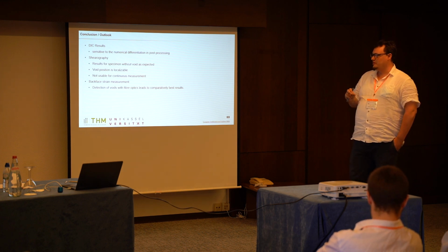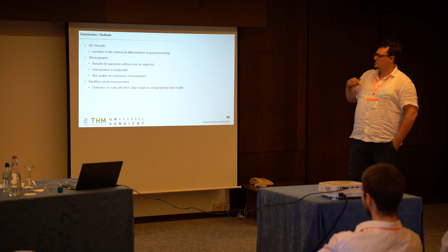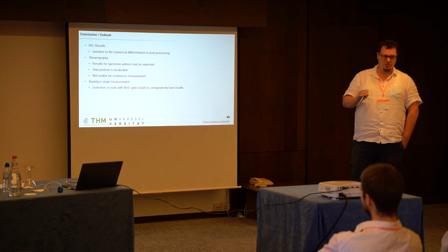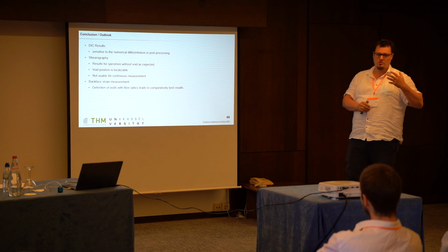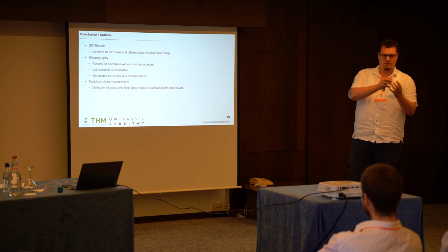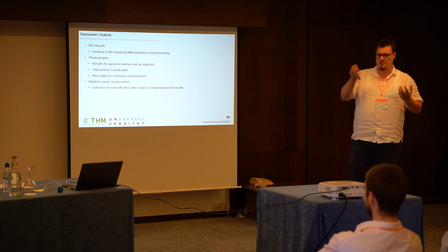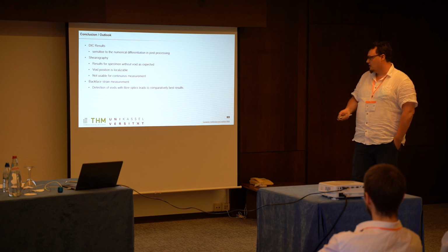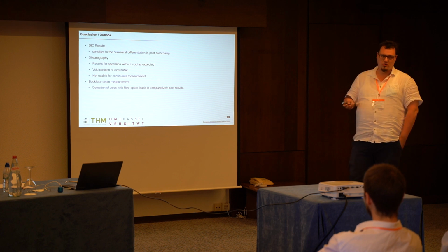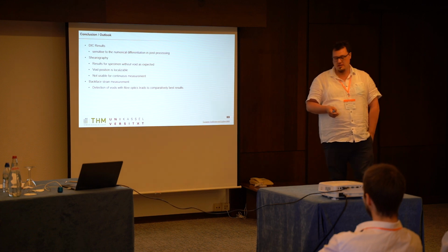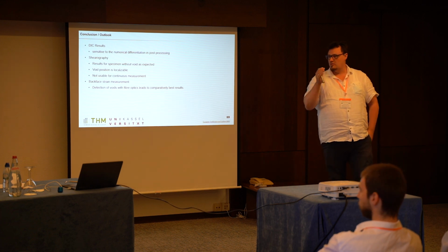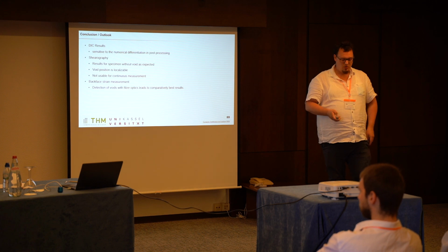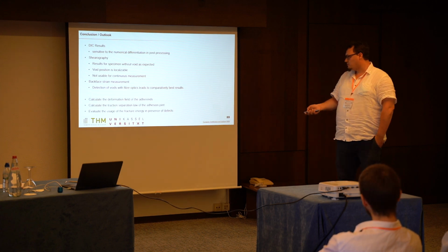But one disadvantage is that it's not usable for continuous measurements. We have to take 5 pictures at one state with a rate of 9 Hertz, and then we have to wait and take the next pictures. The Backface strain measurement shows the comparatively best results. We can detect the void's position and also the void.